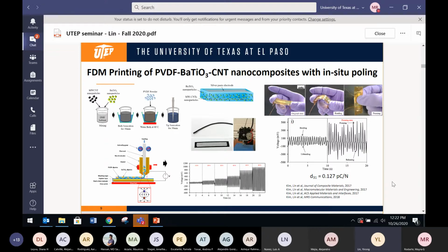The key innovation we're doing here is that we not only made this filament, but at the same time, we did in situ poling, because this piezoelectric material requires high voltage to align the dipoles after the printing process. So we combine both processes into one. As you see in the lower middle, when you apply 10 Newton, 20 Newton, all the way to 80 Newton of force, you see the voltage response from the printed piezoelectric material increasing, right? The higher the force, the higher the voltage. So you can easily use that as a force sensor.